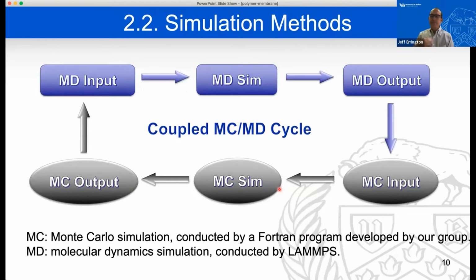So what we ended up doing in the end was using this hybrid Monte Carlo molecular dynamics type of approach, in which we spent some time doing a canonical molecular dynamics simulation. So during one of these canonical simulations, the polymer tethers can sample different configurations. And then at some point, we would stop that. We'd take the output configuration from that, and we would use that as the input to a short grand canonical Monte Carlo simulation. During that, we would allow the water to displace into different positions. We would have water molecule particle insertions and deletions, but the polymer base membrane and tethers would remain static during those simulations. So we repeated this cycle something on the order of 200 times.